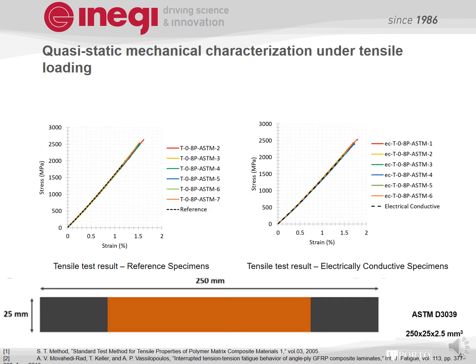Quasi-static mechanical characterization under tensile loading. Tensile tests were conducted on reference and electrically conductive specimens according to the test standard ASTM D3039. Dimensions of the specimen tested were 250 by 25 by 2.5 millimeter of thickness. A total number of 6 specimens were tested according to the test protocol.